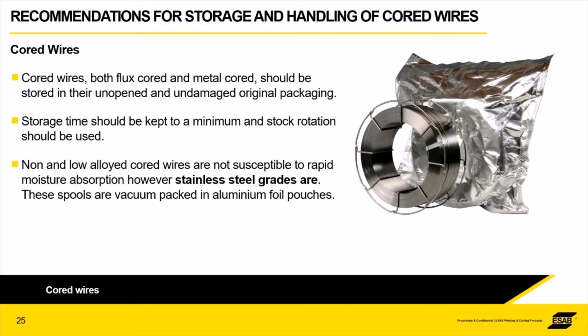Cored wires, obviously these contain flux or metal powders. So it's a tiny tube that contains a flux or a metal powder. The non-alloy and low alloy cored wires are not really susceptible to moisture absorption. The chemistry, the type of materials that we use are not really susceptible, where stainless grades really are. And these grades are vacuum packed in foil pouches for that reason. So obviously you don't want to damage the foil pouch. That's when the time will start, and that's when the moisture can start to get into the wire.